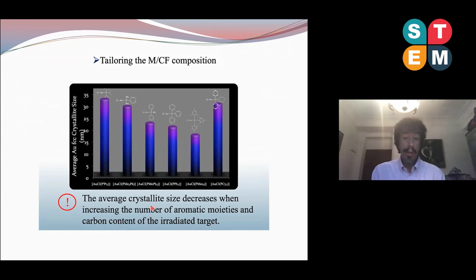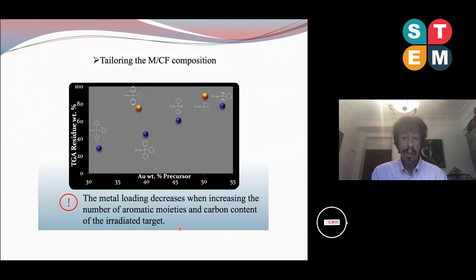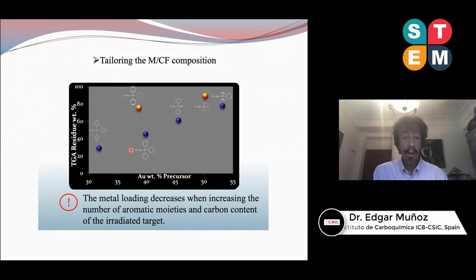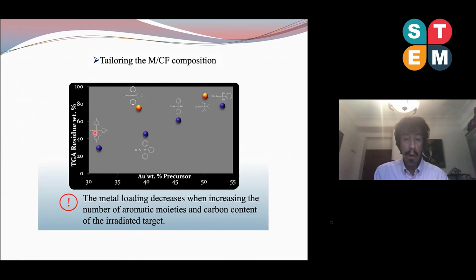So the average crystallite size decreased when increasing the number of aromatic moieties and the carbon content of the irradiated targets. And the metal loading decreases when increasing the number of aromatic moieties. Or when using aliphatic moieties, the metal loading increases.